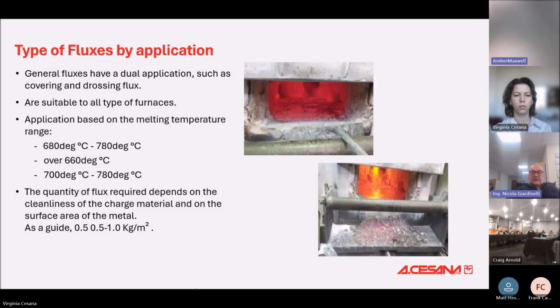Normally, consider the difference between powder flux and granular flux. The powder flux is used at 1 to 5% of the quantity of the metal. With the granular flux, we can reduce the quantity applied in the furnace from 0.05 to a maximum of 1% for every 1 kilo of aluminium.